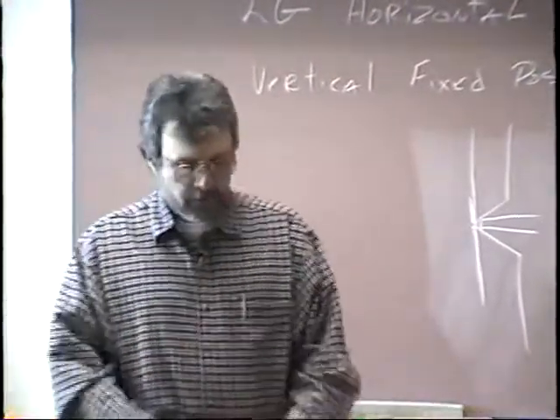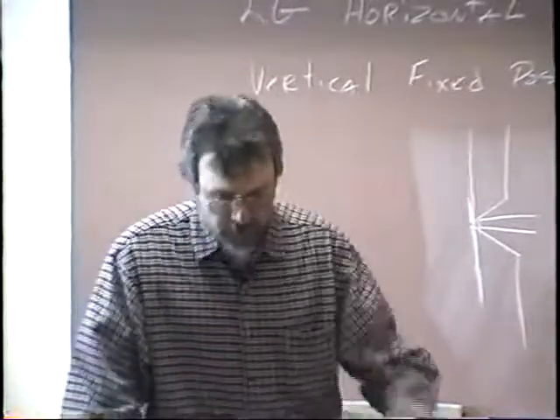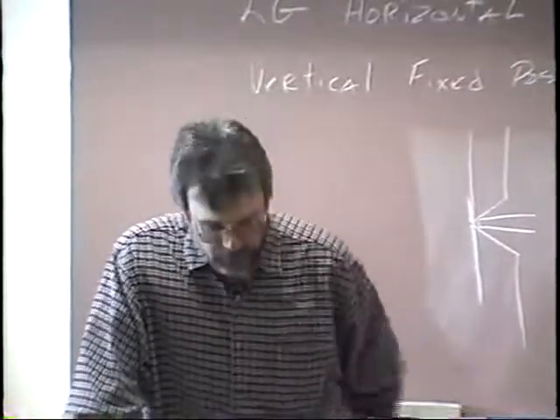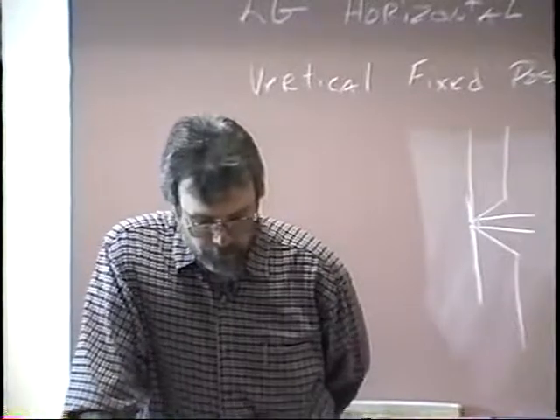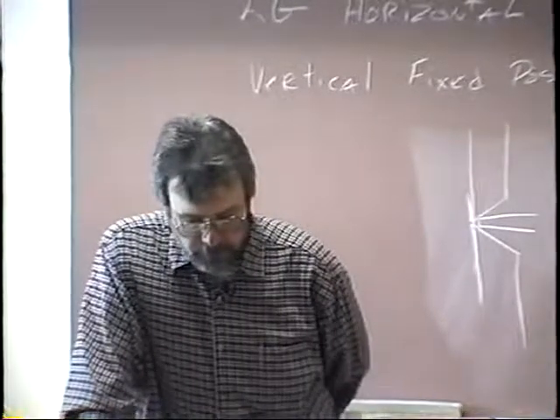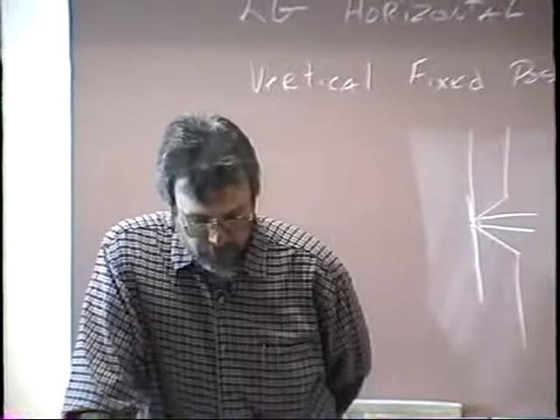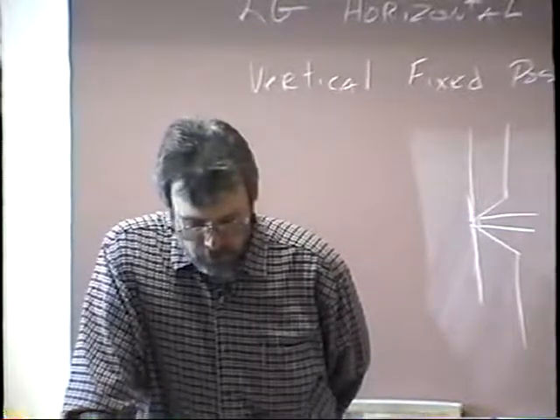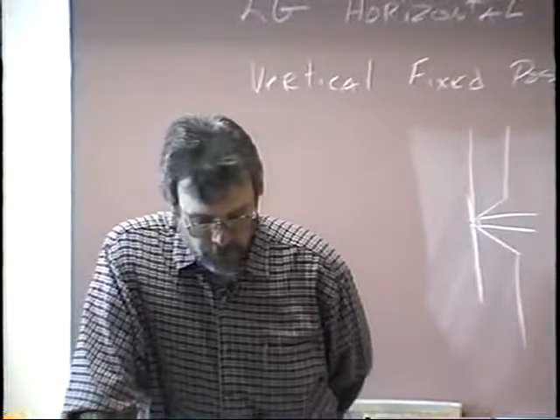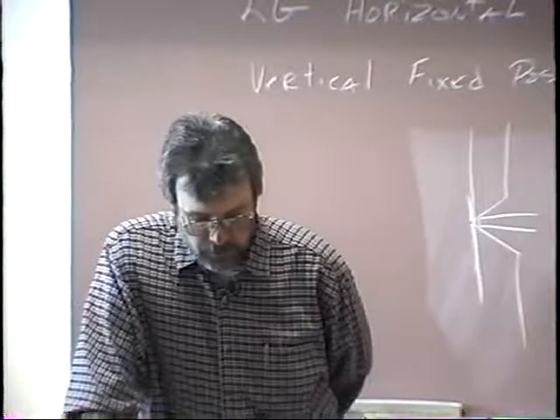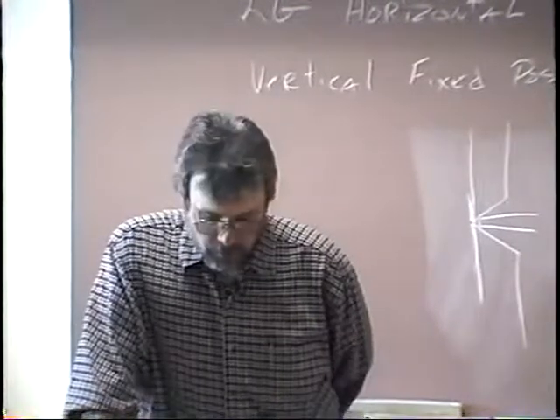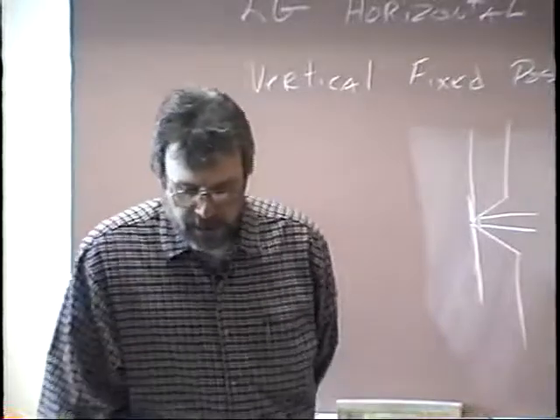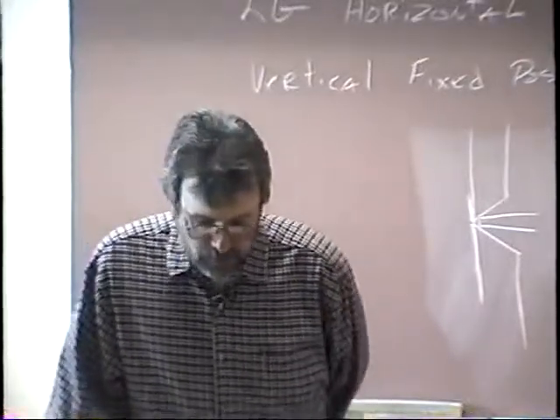Okay, last paragraph on page 138. And incidentally, there's only one question comes off this page. For welding the root bead, the correct arc length is about 1/32 of an inch above the root face. That's what I just spoke about, which is shorter than that used to weld the root bead in the 5G position. The weld should not be started against a tack weld. Usually it is started about 2 inches away from the tack weld. So this gentleman, and this is a good point. I agree with him here.